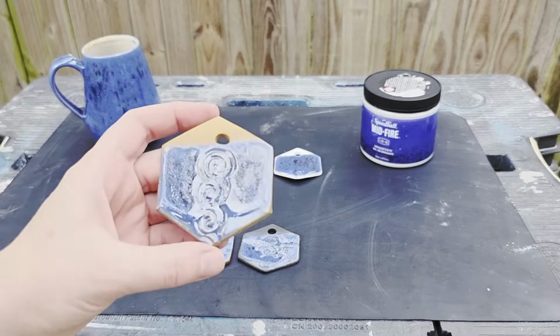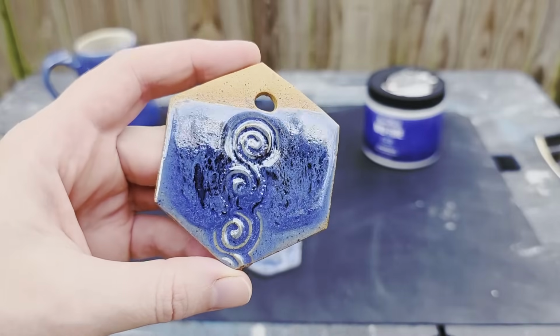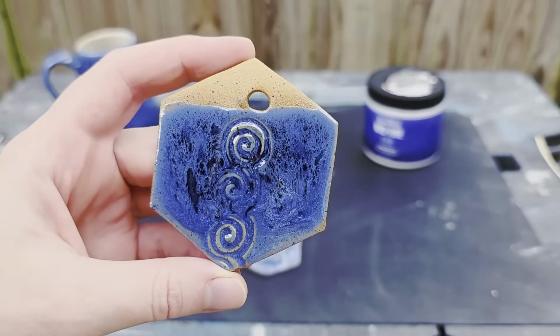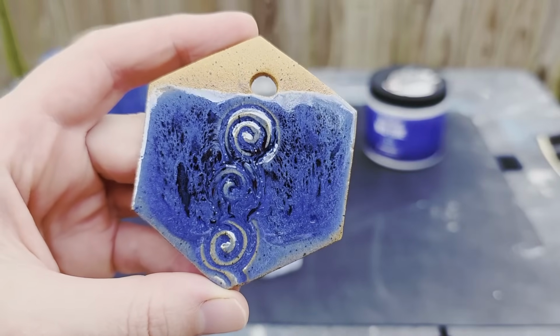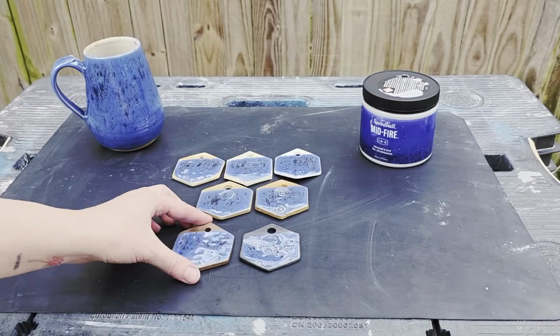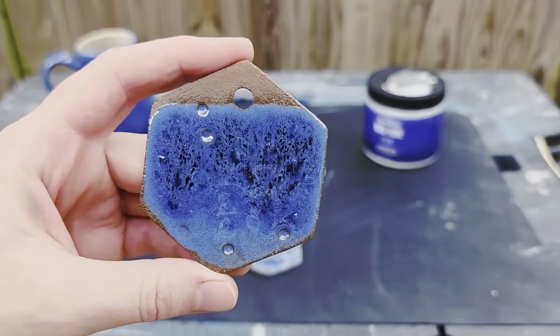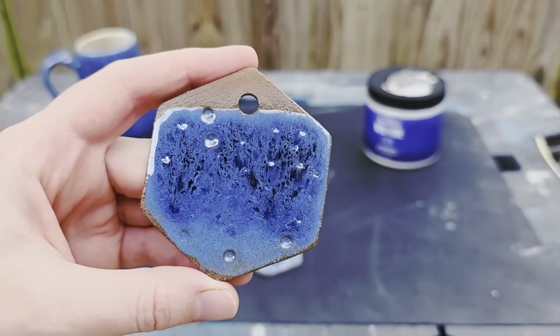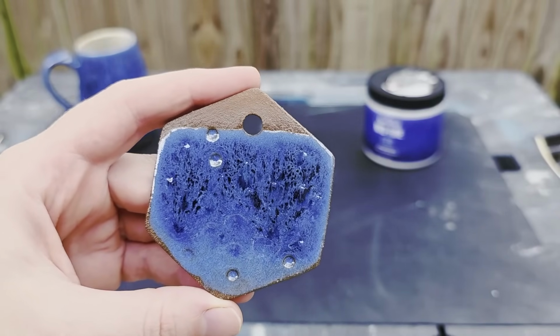The Laguna Speckled Buff tile is also looking great with great color. The glaze is slightly fluid and did break over the texture on nearly the entire tile. The speckles are muted out, and you have more of the mottled effect in areas of thicker application. The red stoneware tile has the smoothest surface on a tile so far. The color is consistent, the glaze is only slightly fluid, and most of the texture has been washed out.